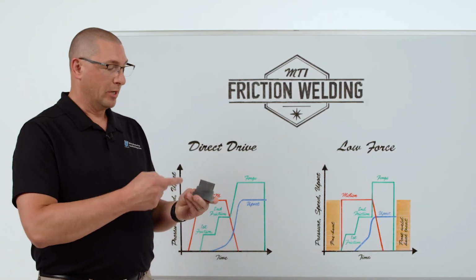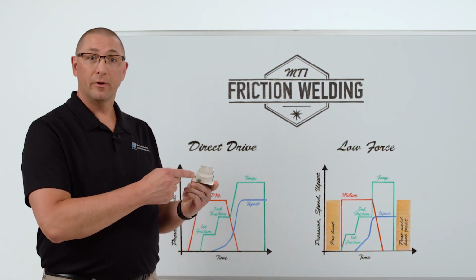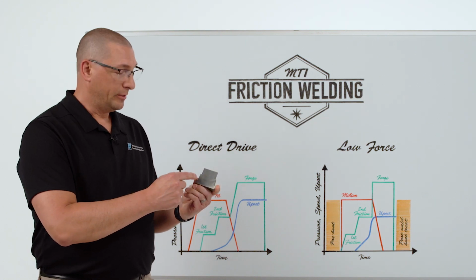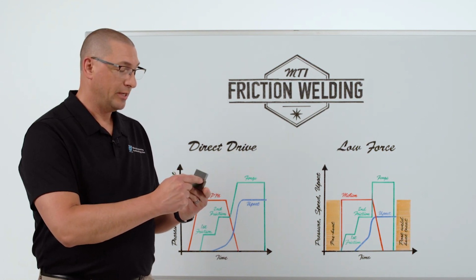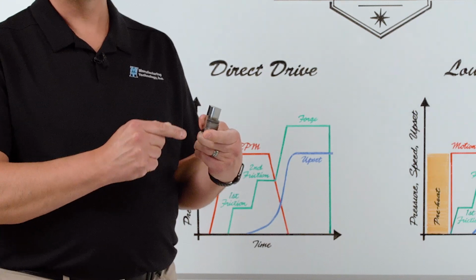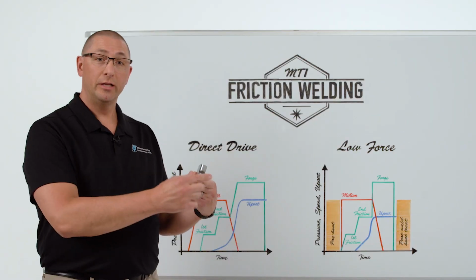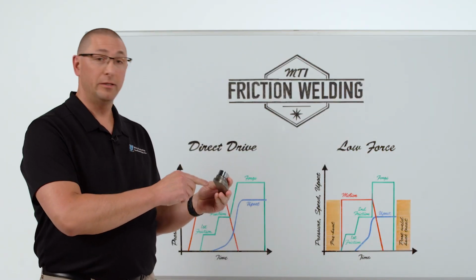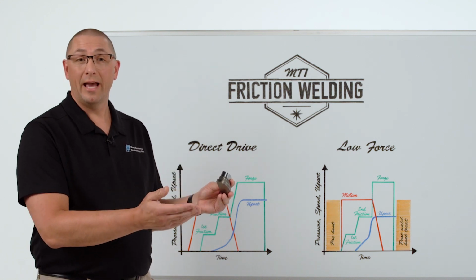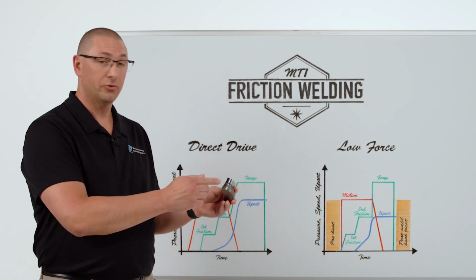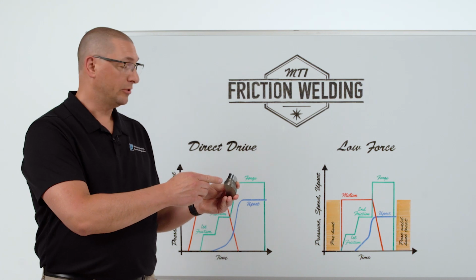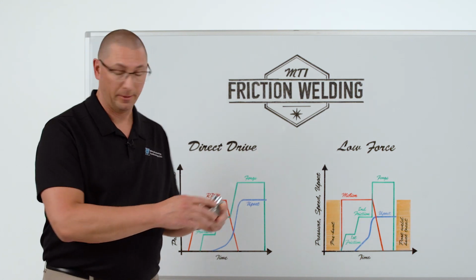Here's an example where we're welding a rod to an eye where the diameter of the eye at the weld interface is slightly larger. You can see this weld curl here is more of a bulge. So turning this off post-weld is much easier. We may not even have to turn it off because there's no stress riser here as a result of the flash morphology.